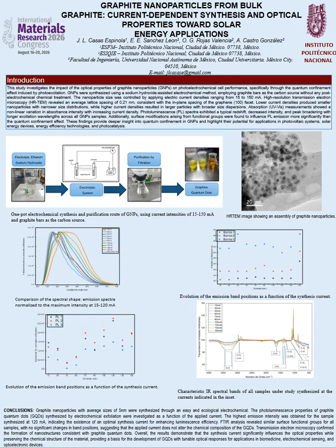In the low energy, a broad peak appears in the region 330 to 400 nanometers, related to n-π* electronic transitions of oxygen-containing functional groups together with transitions involving defect-related states and extended π-conjugated domains, indicating that the nanoparticles are not composed of a single component, but rather a mixture that reflects the heterogeneous surface chemistry of the GNPs, arising from the coexistence of different oxygen-containing functional groups and graphitic domains.